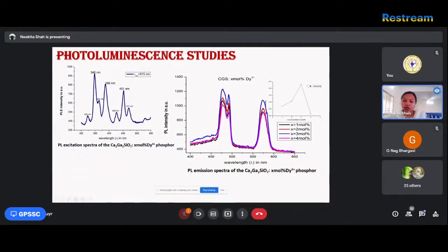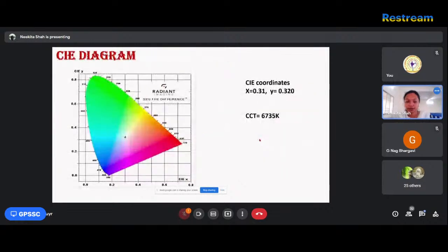Thus, it is concluded that the dysprosium ion is situated at a low symmetry site, and concentration quenching occurs at 3 mole percent doped dysprosium ion. And this is the CIE diagram of the prepared phosphor, and the CIE coordinates are calculated. X equals 0.31 and Y equals 0.320 for 3 mole percent doped dysprosium doped calcium gallium